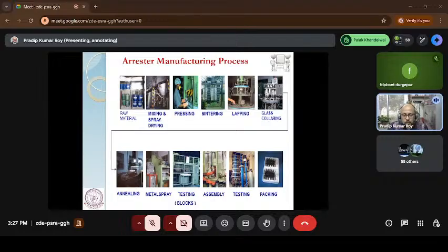Then after this glass coating, we mature the glass through some annealing method. Then we do the metallizing. Metallizing is nothing but we spray some conducting coating on the surface. Then we do block testing. After block testing, we assemble it, and then after assembly we do the product testing. Then after product testing, we do the packing or dispatching. So these are the overall manufacturing process of surge arrester.